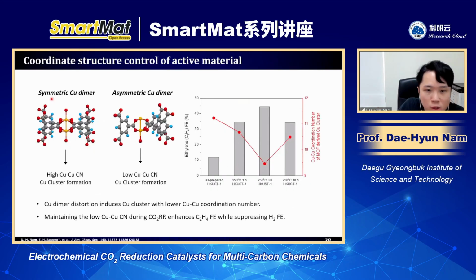So in this way, we now know this dimer will go to a copper cluster. But I found a way to control the coordination number of this copper cluster by modifying the symmetry of this copper dimer. In the case of a symmetric copper dimer, this will produce a copper cluster with a high copper-copper coordination number. But if we make an asymmetric copper dimer, this produces a copper cluster with a low copper-copper coordination number. And we found the ethylene FE trend can be explained inversely by the copper-copper coordination number. It means low coordination number copper is effective for ethylene production. So this is how we can develop copper-based MOFs for CO2 reduction catalysts.